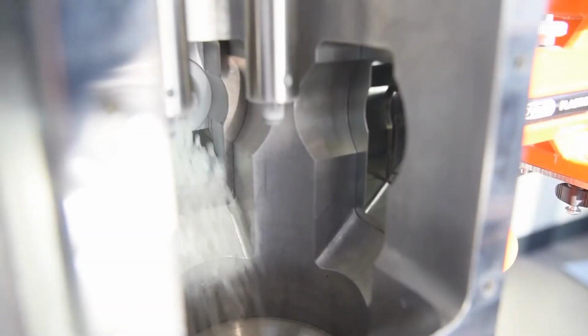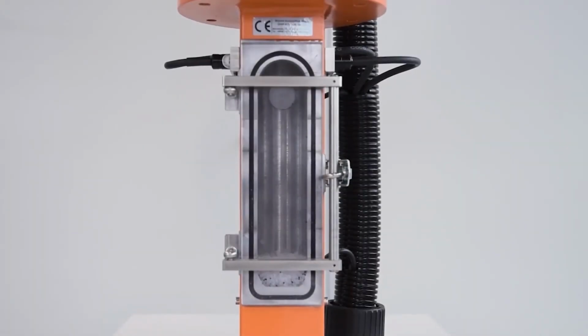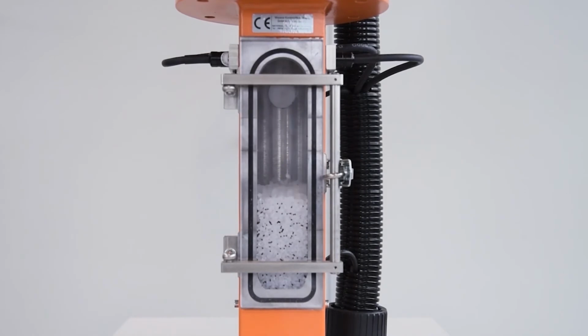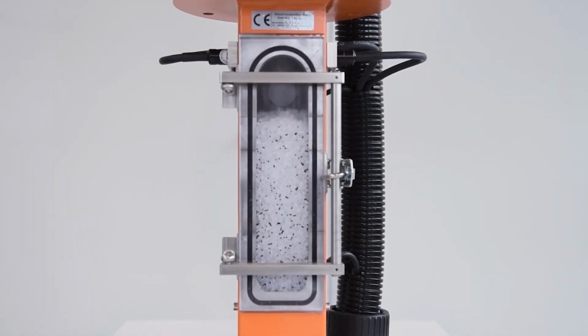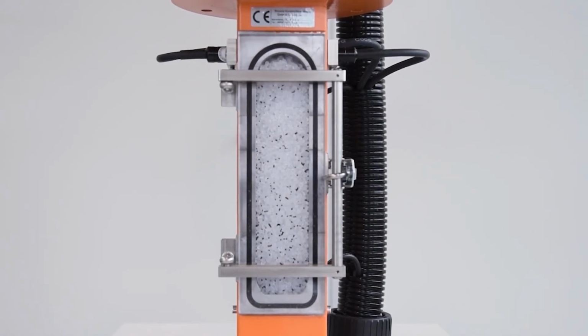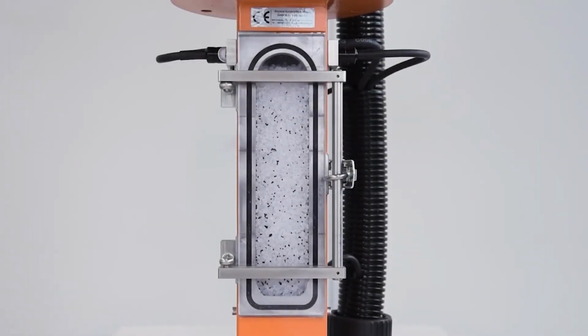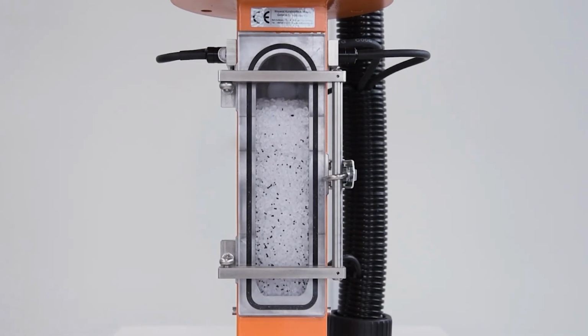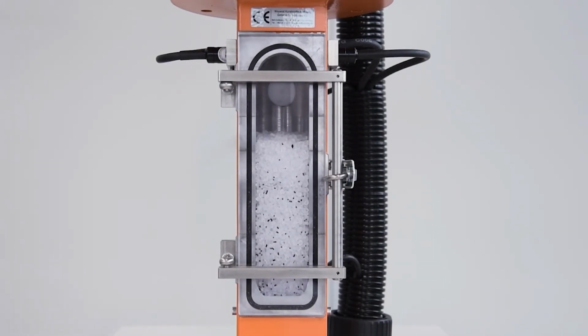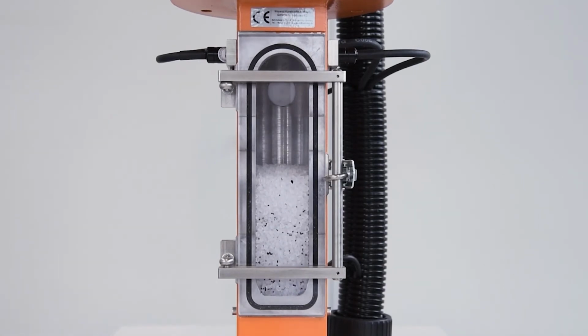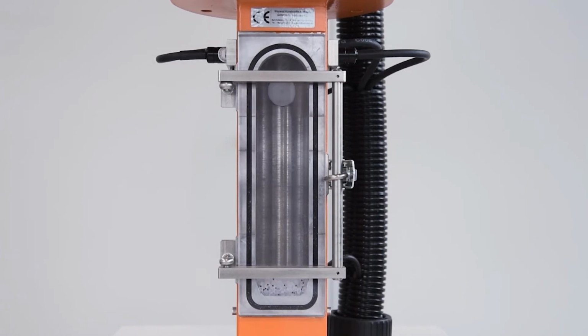You can see here on the left side the compound, on the right side the color pellets falling into the mixing unit. If you have such a mixing unit, what you achieve is a homogeneously distributed color master batch, and there is no such thing as the small pellets falling down and therefore posing a problem in terms of the dilution. And when this mixing unit discharges the material, as you can see here in the film, into the extruder, these homogeneously distributed pellets remain homogeneously distributed, and therefore, once they dilute in the extrusion process, you achieve a perfect color regularity, right?